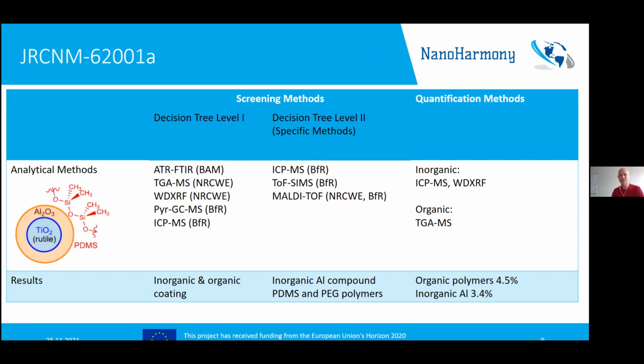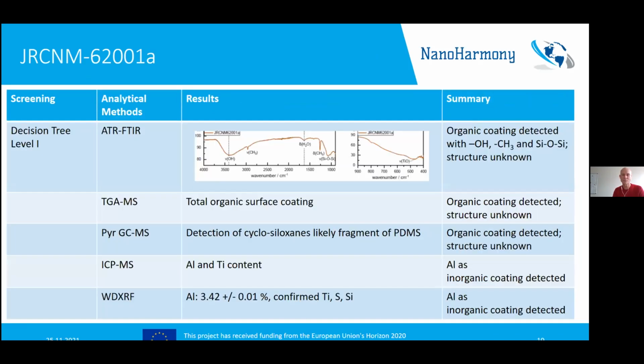So for the titanium dioxide, you can see how we have the titanium dioxide core and the inorganic coating, and actually two different organic polymers coating on the outside, the dimethicone siloxane and the polyethylene glycol, PEG. So with the TGA-MS, we could quantify the mass concentration of the organic polymers. The identity was not revealed with this technique, but this could be revealed with, for example, MALDI-TOF.